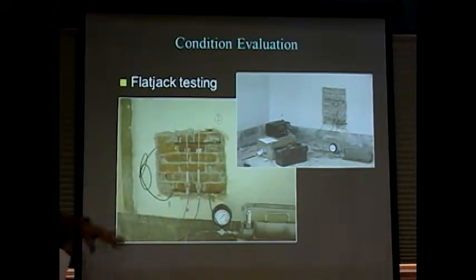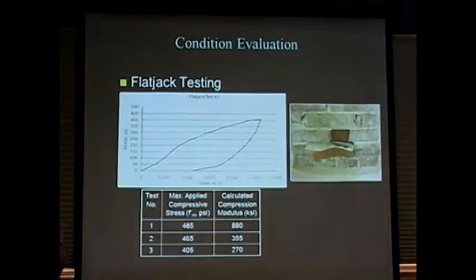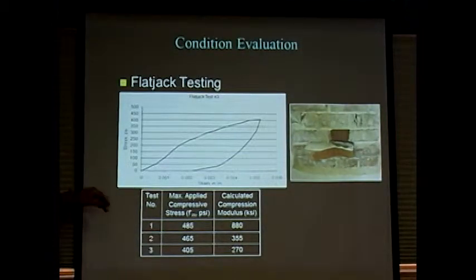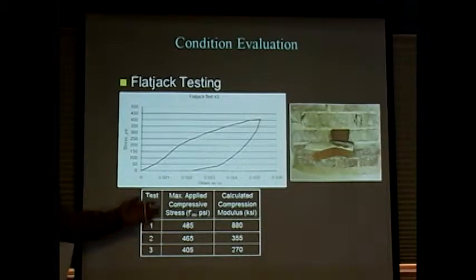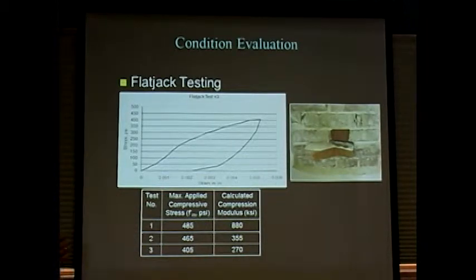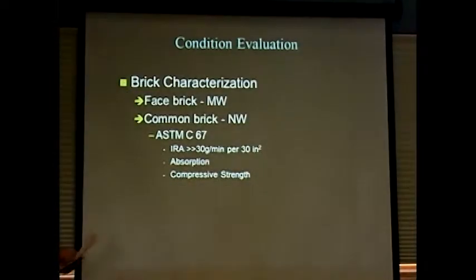When you pressurize it, you read surface strains, and that gives you a real nice, what engineers love to see, stress strain curve. And you know, we ran a series of these tests. Here's 3 of the results from one wall type, and they were showing us a compressive stress in the range of 400 to 500 psi, say. Remember that number, 450 psi. That becomes really important in a minute as we look at some of the bearing stresses that were designed into the system. So, ran some flat jack tests.